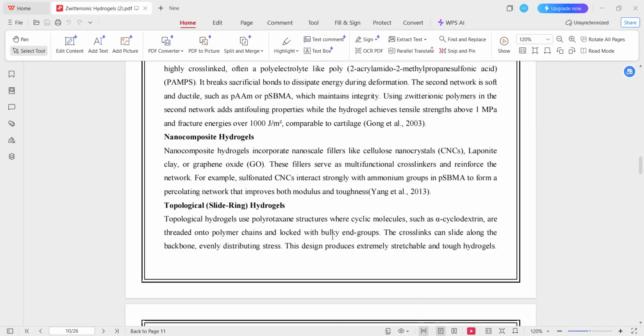They interact with the polymer chains through electrostatic interactions and hydrogen bonding. Under mechanical stress, polymer chains can slide along the surfaces of the nanofillers, allowing stress to be distributed more evenly throughout the network. This sliding mechanism dissipates energy and significantly increases toughness and durability. Importantly, because the nanofillers are present at low concentration and are well dispersed, they do not significantly reduce water content or disrupt the hydration layers responsible for antifouling behavior.